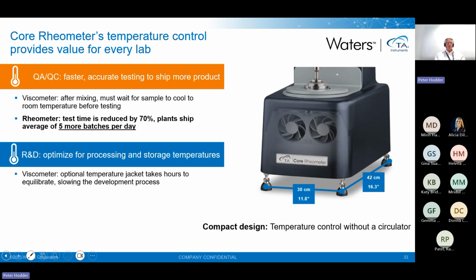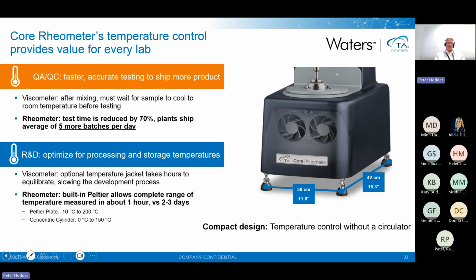If you're in R&D, then of course, in the example with the lubricants, if it takes hours to equilibrate, it's slowing the development process down. But with the Rheometer having built-in Peltiers, you can get the temperature control very accurately, and you can do a whole range of testing within about 1 hour, rather than maybe 2 to 3 days.